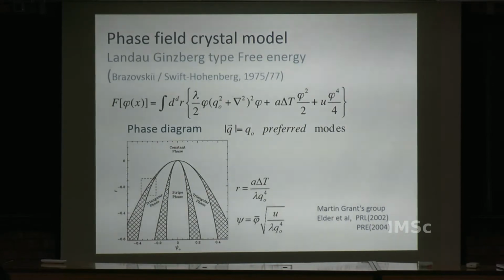This was gotten somewhat accidentally, I would say, because you are preferring a particular scale but not a particular vector. When you get the hexagonal lattice, you have 2 unit vectors at a 60-degree angle, and you can span the whole lattice using these 2 unit vectors. So the system is preferring arrangement along those 2 unit vectors. That's the accident. That's not built in by hand here. The magnitude, the periodicity, the length is built in, but not the vector.